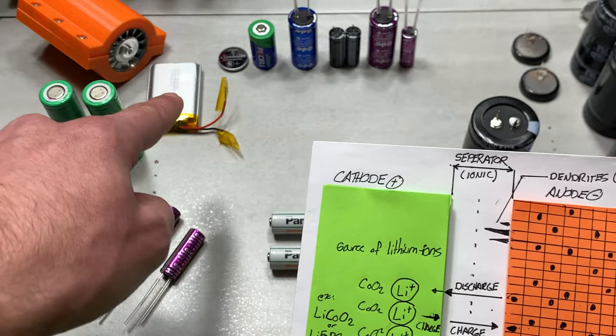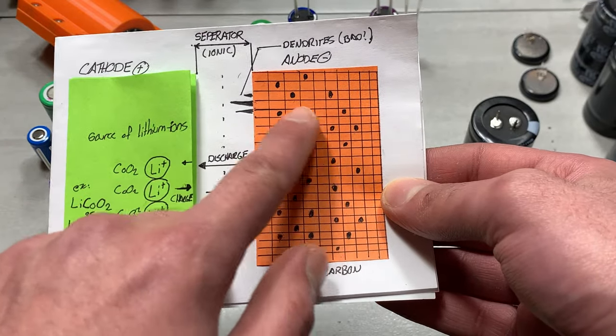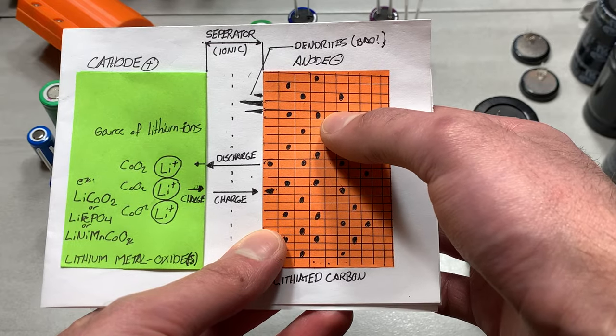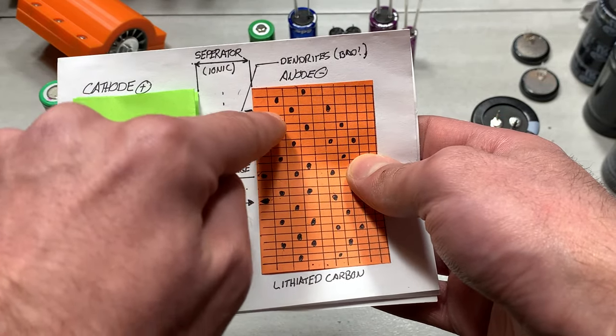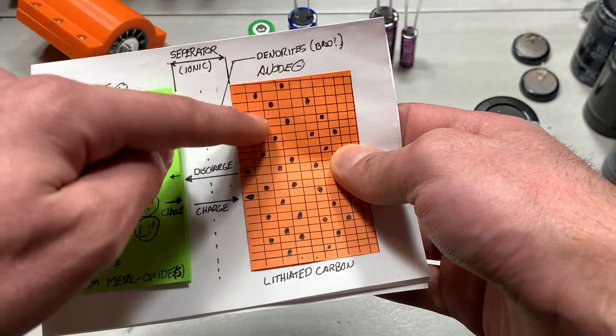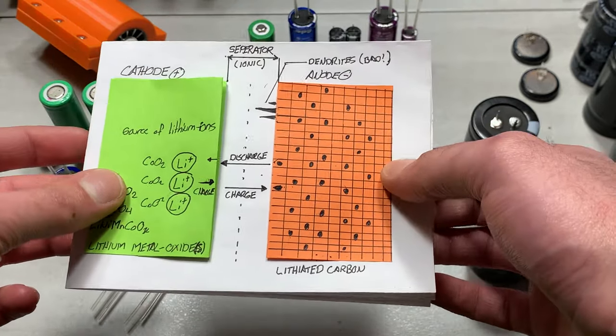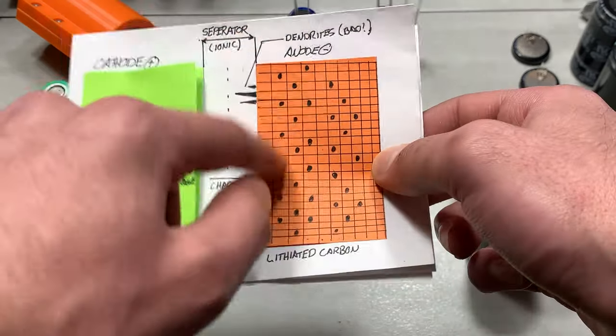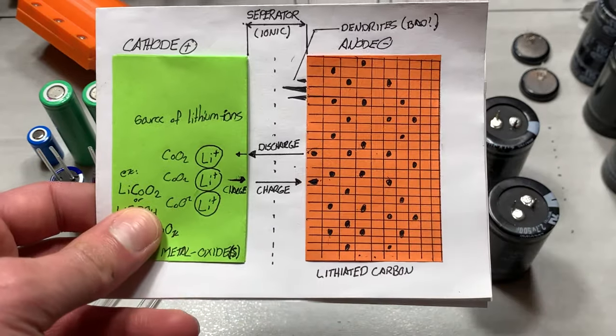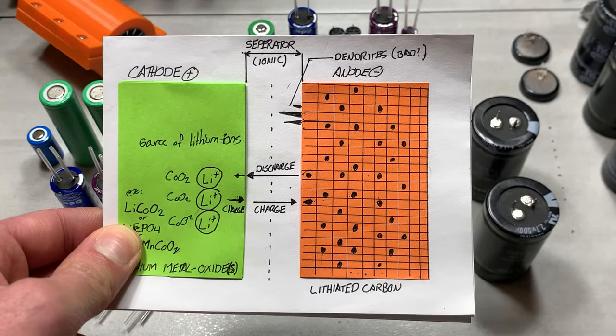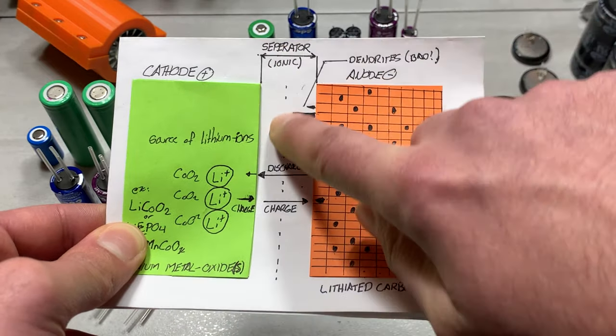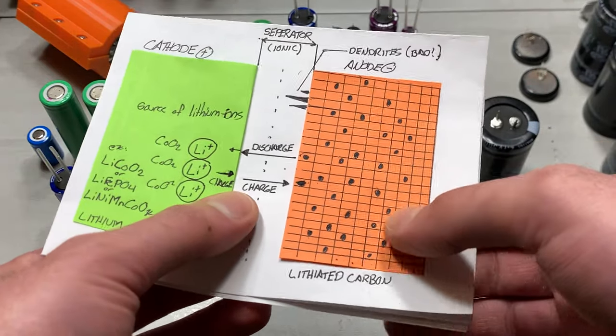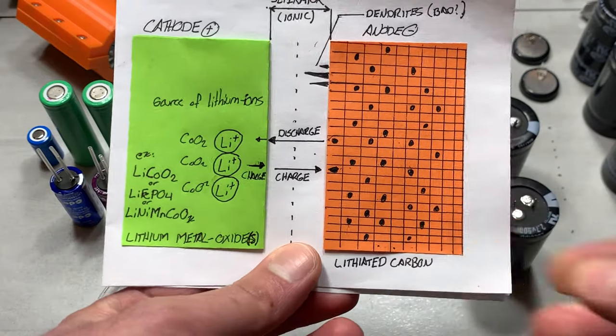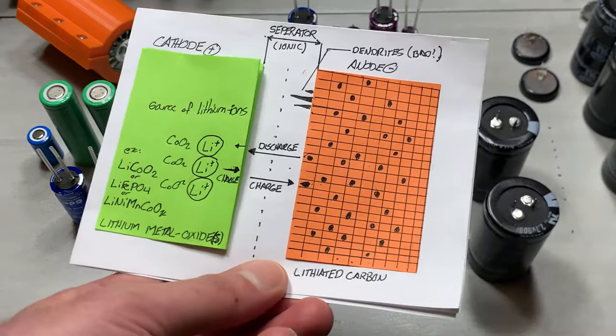So here I have drawn a two-dimensional representation of the inside of a lithium ion battery. And because this side on the anode is actually graphite or activated carbon, I should have technically drawn these as hexagons or semi-hexagons. I was sort of drawing this in a bad position, so I didn't think it would turn out too well, so I just drew a grid. But I think this should not only explain on a surface level what intercalation and deintercalation of lithium ions means, but also go into why I think the separator may play at least a portion of the role in the high charge and discharge rates and low internal resistances of these supercapacitors.